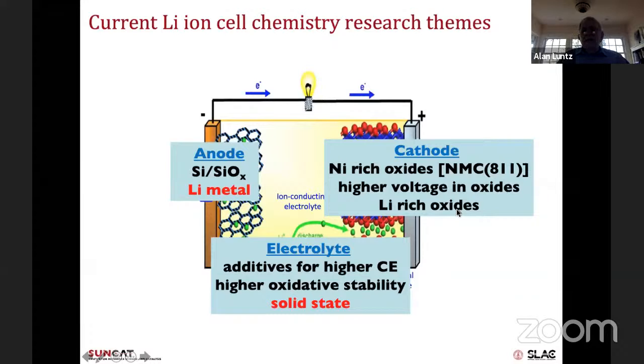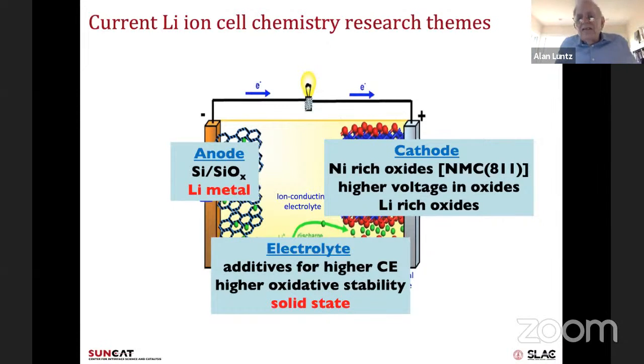is that the cathode particles become much less stable. Particularly they tend to have either phase transitions or they react with the electrolytes. But at any rate, you have problems at the surfaces of these particles, which allow dissolution of some of the transition metals. And this causes all kinds of problems on the anode side. So it's a real problem; it causes voltage fade and a low coulombic efficiency. So there's a lot of work going on in trying to put specific coatings on these materials that will inhibit the problems at the surfaces of the particles.